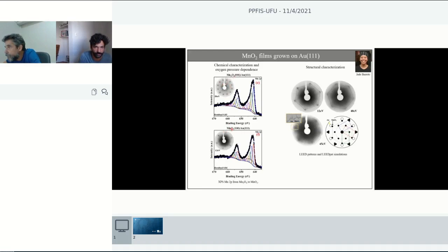This is, for instance, the LEED pattern for the Mn3O4, and then this is the example that you can see. This is quite a different energy here, but still it's a good example that shows the structure. The spot structure that you see is pretty different from the one that you see for the Mn3O4. And then we can judge if this is really the oxide that we expect from the structure of the XPS peak. This is quite an important result to be developed in the next years, because it's the one that's expected to have the highest reactivity, because it's not manganese +2 and +3, but manganese in the +4 oxidation state. And then it's a very unstable situation where it is easy for the manganese to be low coordinated and then later exchange electrons with any molecule that is found on the surface.